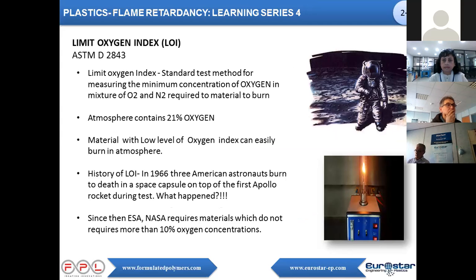We start with the limiting oxygen index. The LOI test follows ASTM D2843. Limiting oxygen index is a standard test method to measure the amount of oxygen required from the atmosphere to burn. Three important things accelerate the fire glow. First one, fire source. Second, fuel or burning material. Third one is oxygen from the atmosphere.